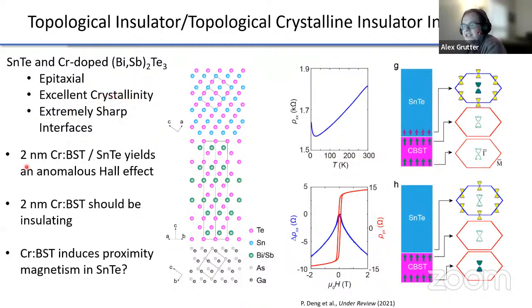What he did was grow 2 nanometers of chrome doped bismuth antimony telluride and see an anomalous Hall effect, a really strong one. The trick is that chrome doped bismuth antimony telluride should be insulating, so you don't expect to see any signatures of transport through the chrome doped BST. So where is this anomalous Hall effect coming from? The question is whether the chromium doped bismuth antimony telluride is inducing proximity magnetism in the tin telluride.